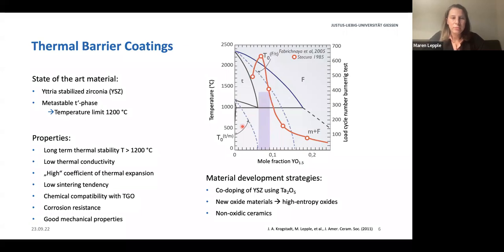The state-of-the-art material for thermal barrier coatings is yttria stabilized zirconia. So, here you can see the phase diagram, starting from zirconia with increasing mole fraction of yttria. And yttria stabilized zirconia is used because it has a very good thermal cycling behavior, as you can see here with the red dots. And this is due to the formation of the metastable T prime phase.